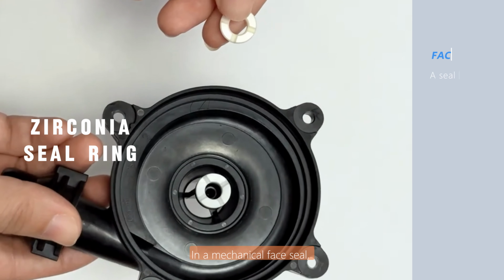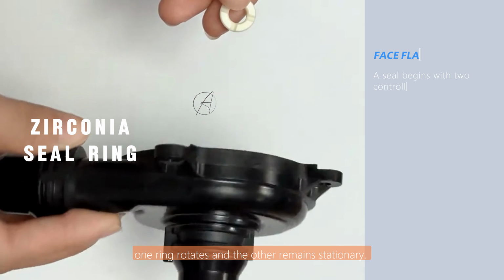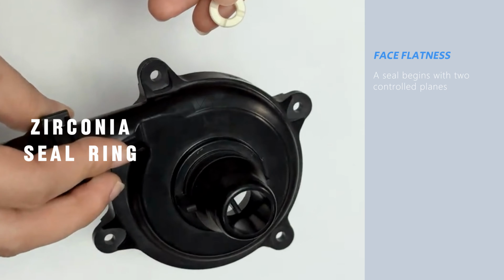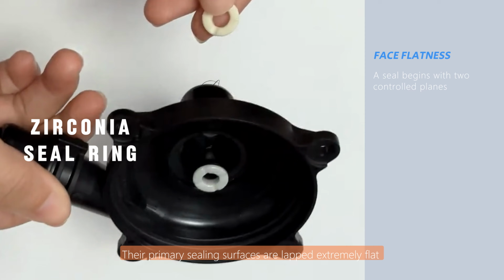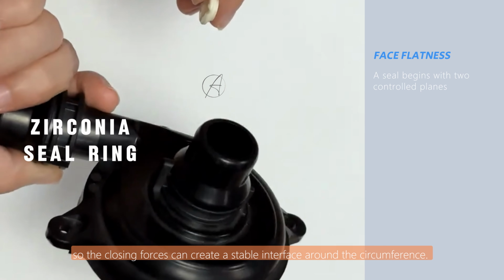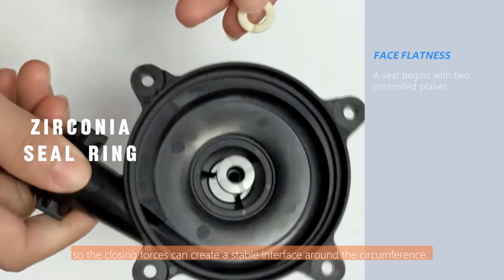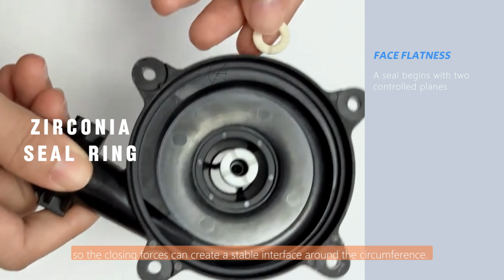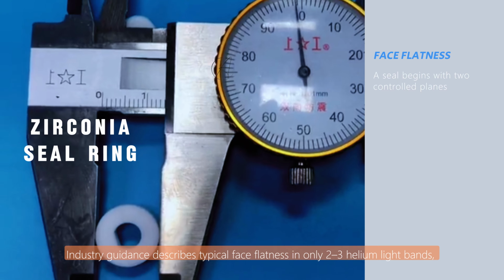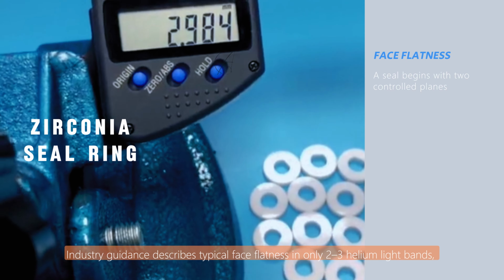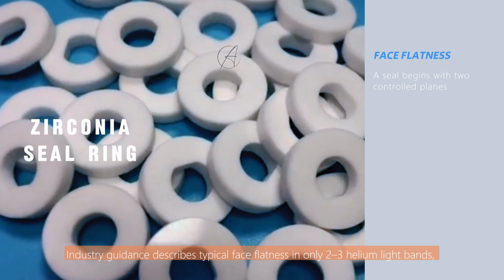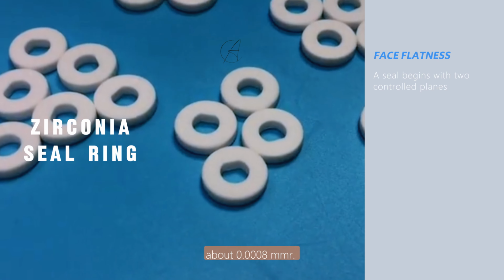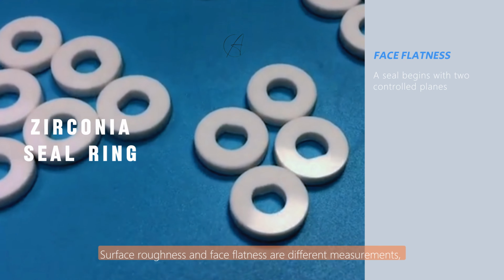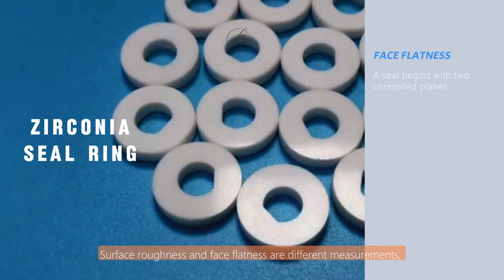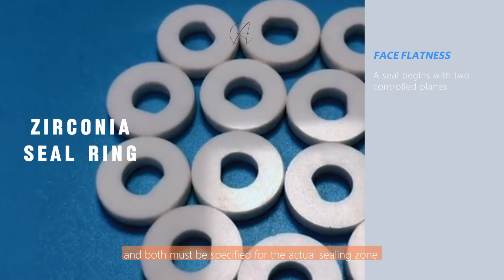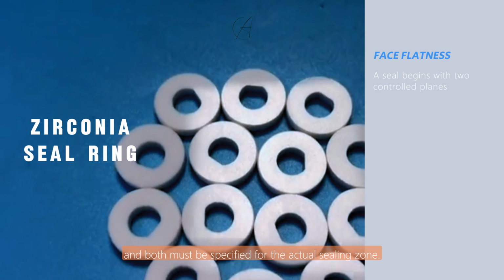In a mechanical face seal, one ring rotates and the other remains stationary. Their primary sealing surfaces are lapped extremely flat so the closing forces can create a stable interface around the circumference. Industry guidance describes typical face flatness in only 2 to 3 helium light bands, about 0.8 of a micrometer. Surface roughness and face flatness are different measurements, and both must be specified for the actual sealing zone.